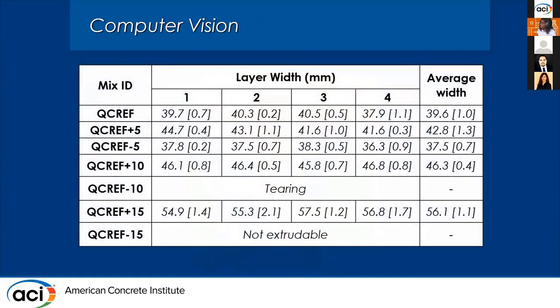And these are the actual variations for the main experiments. The reference, QCref, as I said, was designed for 1.5 inch width, so it was around 38, 39 millimeter, based on the design. And then various amounts of water, which affect the width of the layer. If you see the variations and the average width for 4 layers for each experiment, you can see that at each variation level, even the lowest ones, we are able to see a significant change in the width of the layer, and there is no overlap. So basically we can see a meaningful change in the layer width as a result of changing the water content.